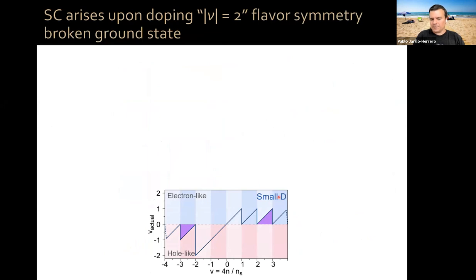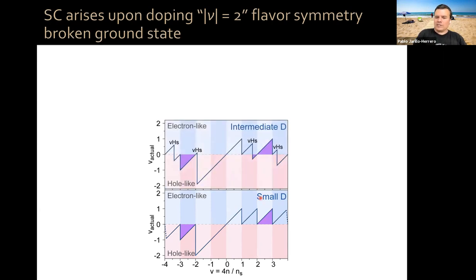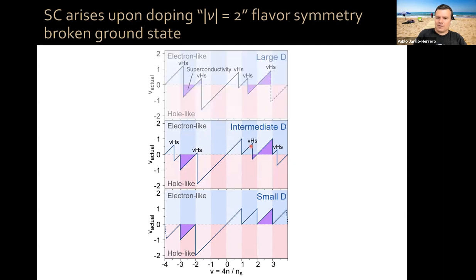At small displacement field, we have this cascade of phase transitions. So you have resets at each integer that's bounding your superconductivity between 2 and 3 and -2 and -3. In this region, we know that we have a phase transition. We just underwent a phase transition to a flavor polarized state with two open Fermi surfaces. Two are fully polarized and two are sort of empty. As we increase the displacement field, we see that there is a Van Hove singularity that seems to kick in the phase transition before nu equals 2, and before nu equals minus 2.